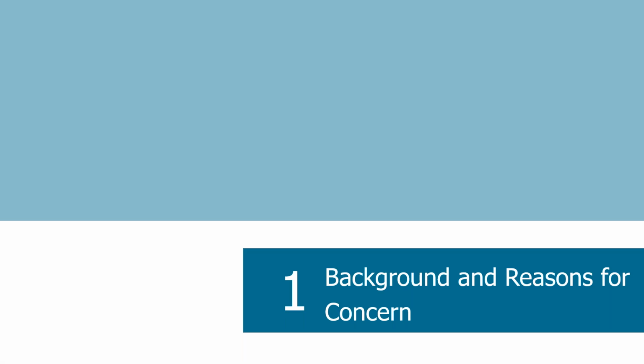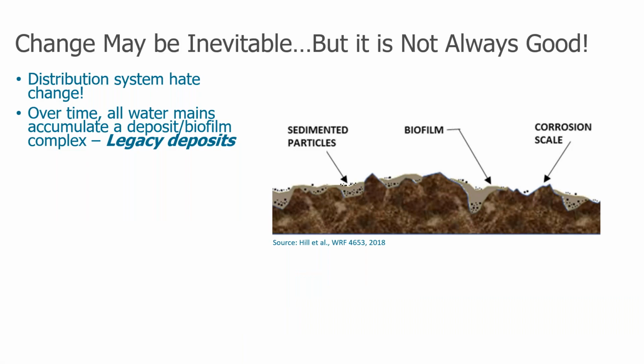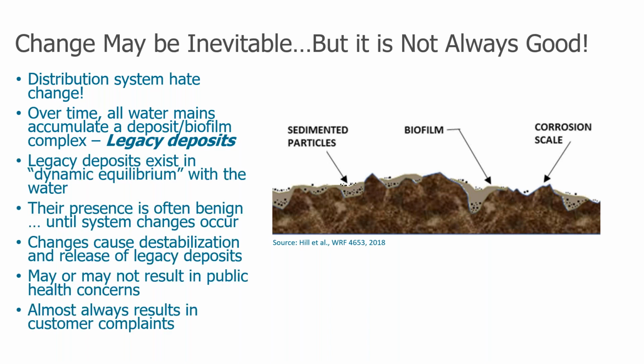So beginning with background and reasons for concern. We all know change is inevitable, but it is not always good. Distribution systems hate change, because over time, all water mains accumulate a deposit biofilm complex that we call legacy deposits. And this is really a complex of corrosion scale, biofilm, and sedimented particles that all occur together in what we call a dynamic equilibrium with the water. They can subtly adjust to minor changes in daily flows and maybe subtle changes in chemistry, but when we have larger scale changes, we can get destabilization and then release of these deposits. Now, these releases may or may not result in public health concerns, but they almost always can result in customer complaints.